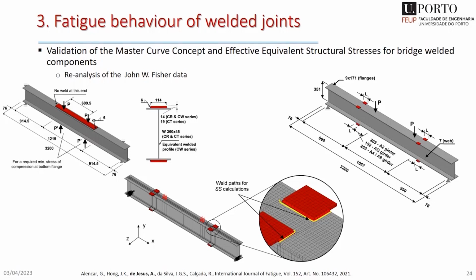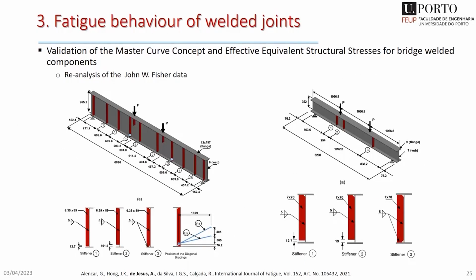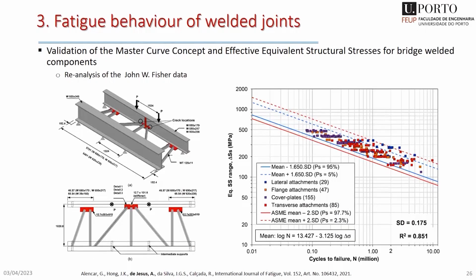So I'm talking here of, for example, girders with some attachments on the flanges, welded attachments, as you can see here. Then we have other longitudinal girders with stiffeners. And for those stiffeners attached to the web, we have some gaps between the end of the stiffener and the flanges, which generate some distortions on the webs. We have also some bracings, which increase the distortion in the webs. We also have models of bridges with girders connected to each other with horizontal girders, and asymmetrical loadings, generating again these distortion effects on the structure. So, multi-axial stress fields.